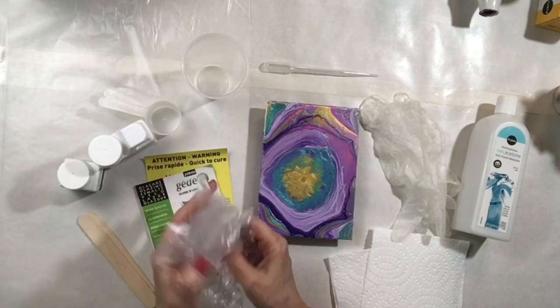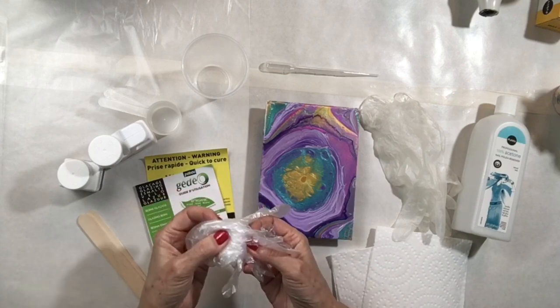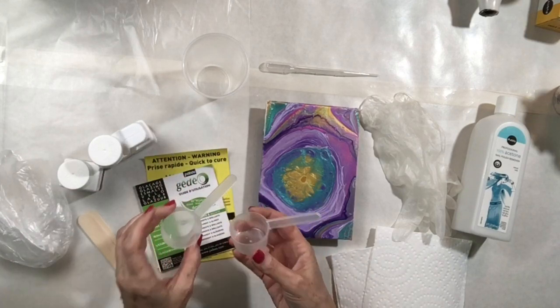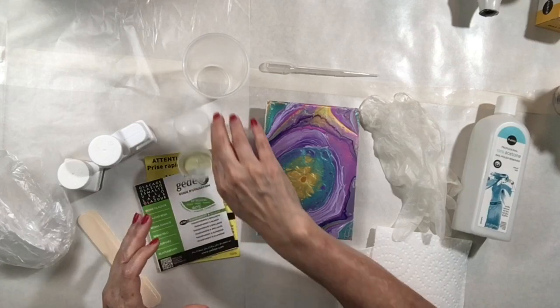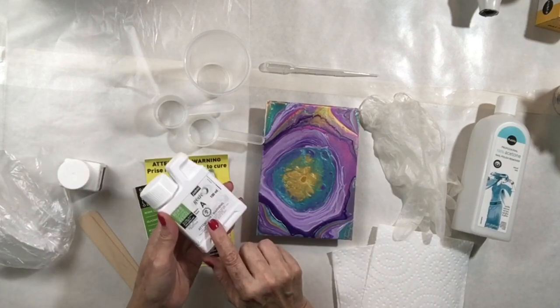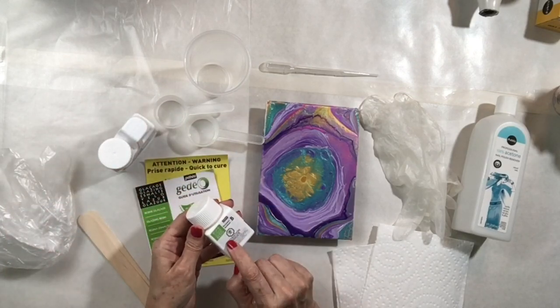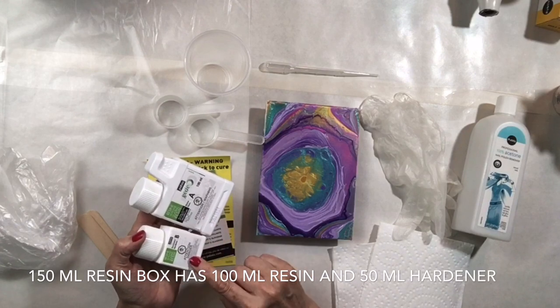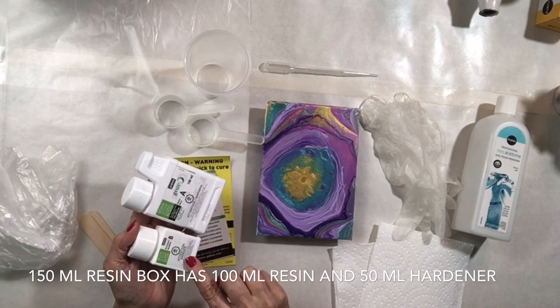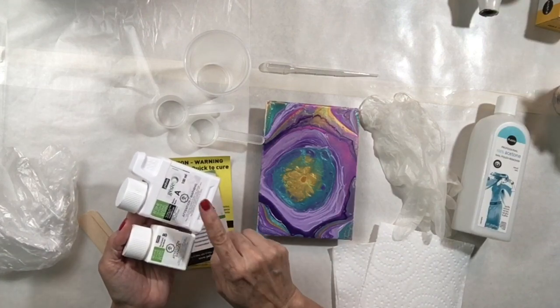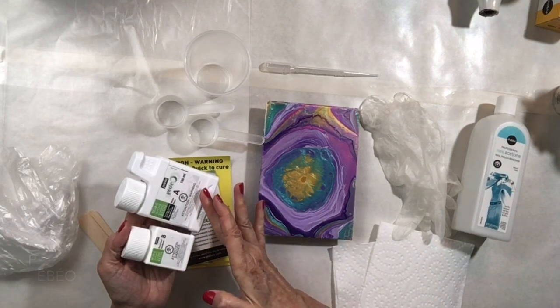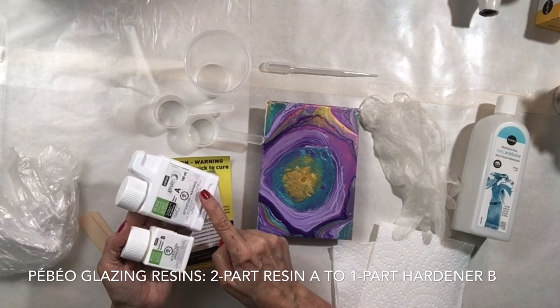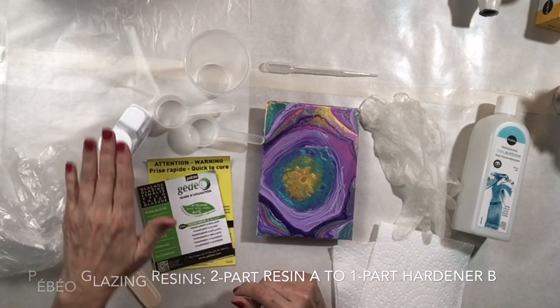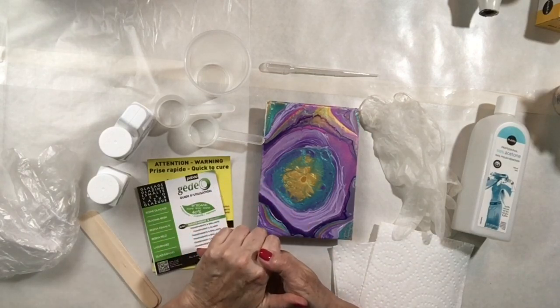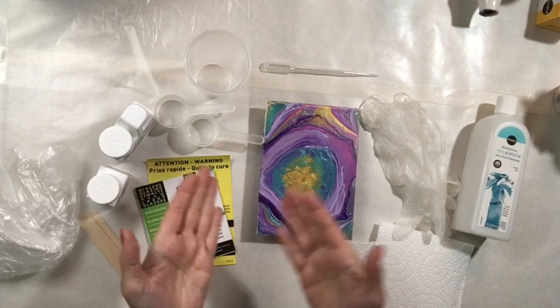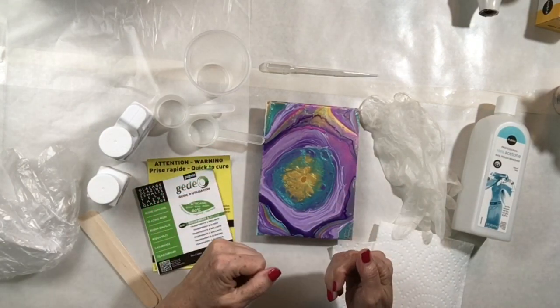You're going to receive some gloves. So if it's your first time using resin, there will be a set of gloves in there. You have your measuring cups, so one for the part A and part B. This is an epoxy resin that requires a resin part A and a hardener part B. Now you'll notice that there's a difference in the size of these two containers. This has 100 milliliters in it, and this has 50 milliliters in it. Why is that important? Well, different resins mix at a different rate. So this is a resin that mixes two parts resin to one part hardener, two parts A to one part B. That is why we have different size containers. But even if you receive them in the same size container, make sure that you read the directions and you know for the resin that you're using how much hardener and how much of the resin you're going to need.